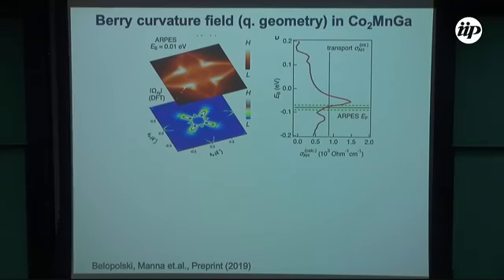So one thing we can do, we can take the ARPES band structure, these 3D Weyl nodes and loops, and optimize the DFT, because now I have the parameters from the real material. And then once we do the optimization, I can calculate the Berry curvature field, kx, ky. Now I can calculate transport properties, because the Berry curvature field is related to the intrinsic part of the anomalous Hall effect. Also from experiment ARPES, we know where the Fermi level is, and the Berry curvature calculation requires knowing the Fermi level, how much you integrate from where to where, right? So we do that for a real material.